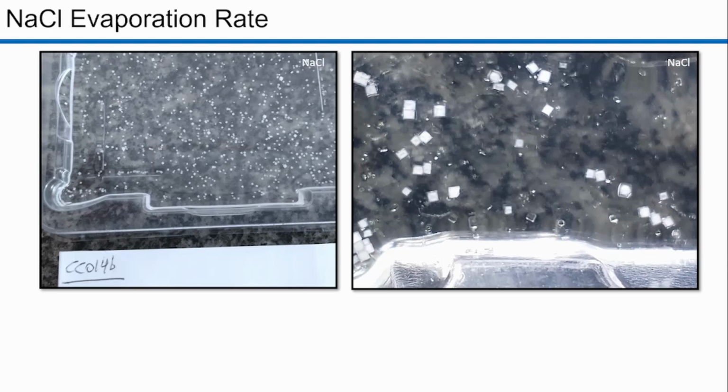I have some more images about this evaporation rate over here, so you can see from this test that we have first some white crystals forming, right? They formed by evaporation to the environment, and then some new crystals formed, but these new crystals formed transparent under the same conditions, just because there were a bunch of opaque crystals before. Now the new crystals are transparent, and not only that, but the old crystals are also getting a transparent layer due to this new evaporation.